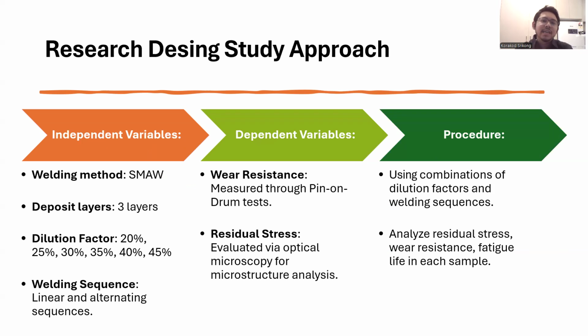Moving on to the research design. My research design aims to address the gap. I used shielded metal arc welding to apply 3 layers of hardfacing with 6 different dilution levels, ranging from 20% to 45%, and 2 welding sequences, including linear sequence and alternating sequence. To evaluate the results, I measure wear resistance using pin-on-drum testing and measure residual stress through the microscope. This experimental approach can provide the optimal parameters which improve wear resistance and reduce stress.